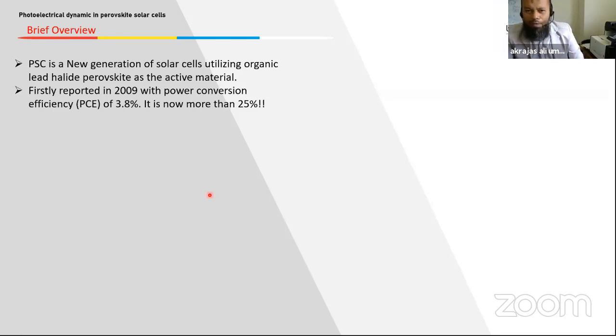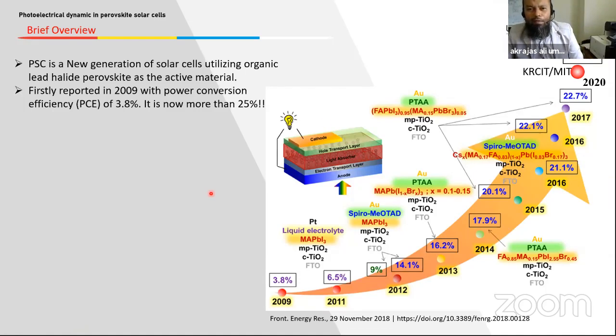Perovskite solar cell, as we know, is actually a new generation of solar cell that utilizes hybrid organic-inorganic lead halide perovskite as the active material. This was first reported in 2009, where perovskite was used as a sensitizer in the dye-sensitized solar cell with an efficiency of around 3.8%, and the performance was improved to 6.5 within 2 years. But because organic halide perovskite is actually an ionic crystal, it is easily dissolved in liquid electrolyte. So in this case, stability has become the main concern.